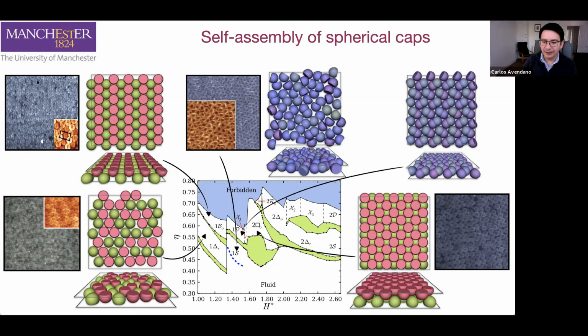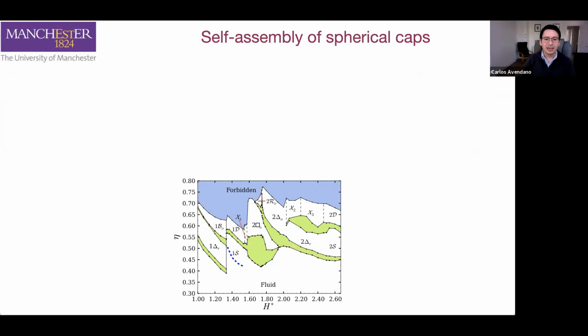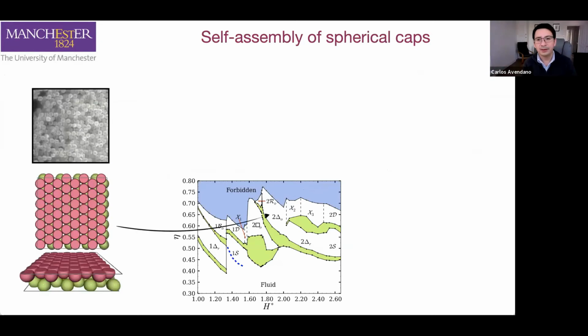After we have a square layer, if they are spheres, we will expect to have the formation of the hexagonal layer once that we increase a little bit more the distance between the particles. And indeed, that's what we observe. And again, that's in agreement with the experimental observations.